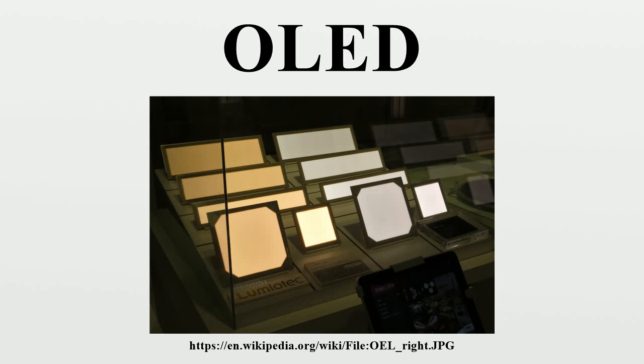In the same year, Dow Chemical researchers patented a method of preparing electroluminescent cells using high-voltage AC-driven electrically insulated 1 mm thin layers of a melted phosphor consisting of ground anthracene powder, tetracene, and graphite powder. Their proposed mechanism involved electronic excitation at the contacts between the graphite particles and the anthracene molecules.